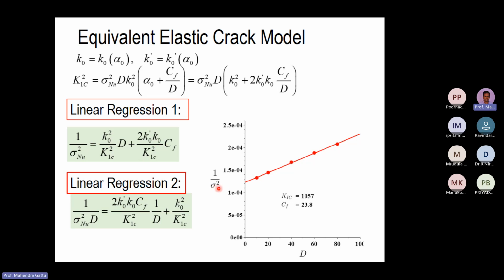From FEM simulations, we can get sigma N value and D value, and if you plot it, you get a curve like this. The slope of this line is equal to K naught square by KIC square, and we can find out this KIC value, which is the fracture toughness. From this intercept, you can calculate this value. We already know KIC, so from that, we can get the cf value, which is the material characteristic length. So these two fracture properties we can determine.